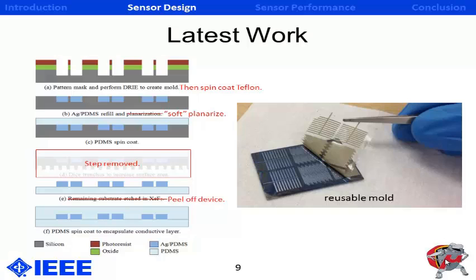So the latest work since submission of the paper involves the coating of Teflon after the mold is created. This is to utilize the anti-stick properties of Teflon between the PDMS and the silicon mold. Then something called a soft planarization is done, which is just planarizing the conductive polymer in the uncured state. It's cured, and then the PDMS is spin-coated, and this device can simply be peeled off. So no need to etch the mold or get rid of it. You can just reuse the mold, and it greatly reduces fabrication time. And then, as usual, the backside is encapsulated in PDMS.